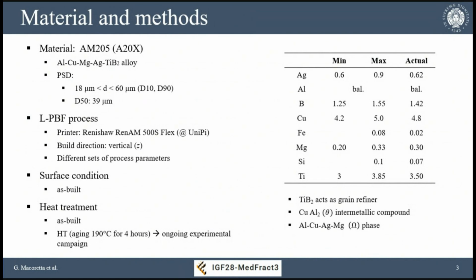to increase its printability and reduce its tendency to produce hot cracks, which is the problem of printing aluminum alloys with L-PBF and also in welding, it uses titanium diboride that acts as a grain refiner because it cannot be melted by the temperatures we can reach in our molten pool. So we have solid material that acts as a grain refiner, and in this way we can avoid the occurrence of hot cracks.